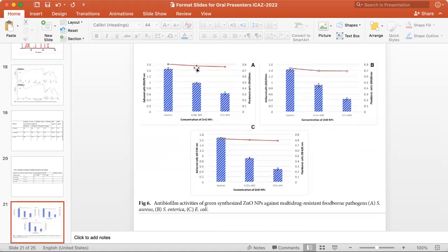Then a quantitative method was also employed by using the microtiter plate method. Absorbance was measured at 570 nanometer, and you can see here in case of control cells, absorbance values were high, indicating a greater number of adhered cells. Whereas when cells were treated with nanoparticles, there was a significant reduction in the number of cells attached to the surface of the microtiter plate.